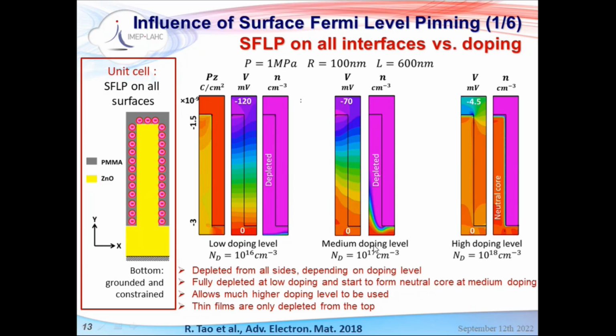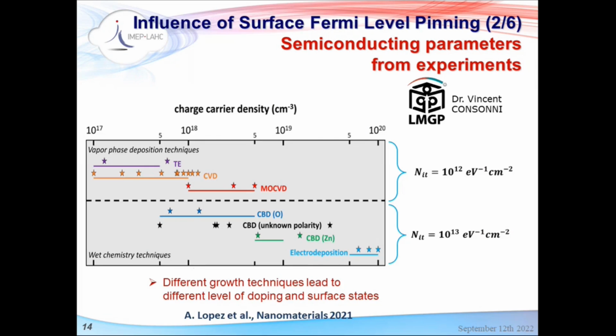As you increase the doping level, you will start seeing a neutral zone, meaning that you have free electrons inside, and that will reduce the overall potential. And eventually for high doping levels, you cannot control this anymore, and you will have, again, a very low potential from the device. So actually what I show here is that, because of these traps that we added, we can exploit higher doping levels compared to previous models. So this could explain why these devices actually work.